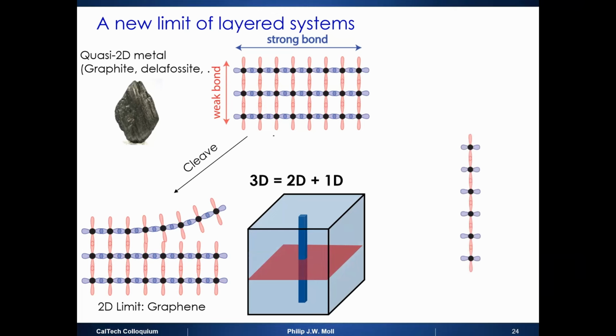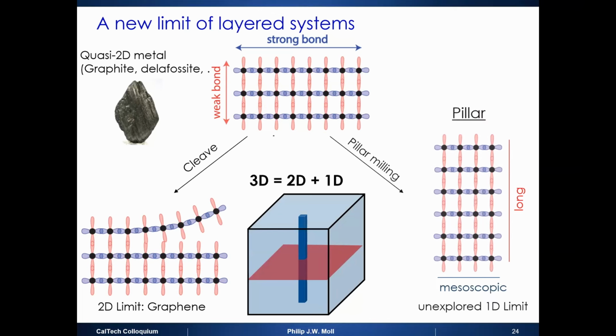And formally speaking, that's an atomic chain. It's a molecule of carbon that has some very unhappy carbon-carbon bonds. This, of course, will explode immediately. So this is pointless. But what if you make it a little bit bigger so that you can kinetically stabilize the object? Think of it as graphite nanoflakes or graphite microflakes that you stack. This is horrible. You never want to do this, like stacking 10,000 graphene sheets. But you can cut this out of graphite and think about what actually happens in this one-dimension limit.